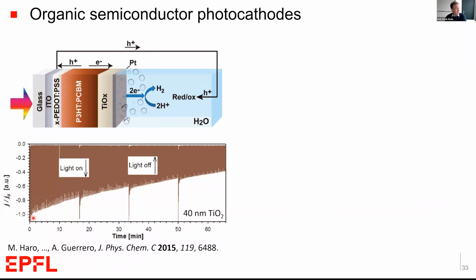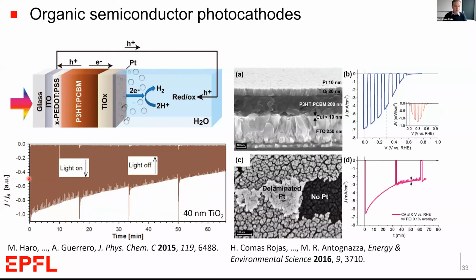This is the photocurrent as a function of time under these light chopping conditions. And after only 1 hour, the photocurrent dropped by a factor of 2. A similar drop was observed in this EES paper in 2016, despite initially having pretty high photocurrents, up to 7 milliamps per centimeter squared. After only 1 hour, this dropped to below 3 milliamps per centimeter squared.